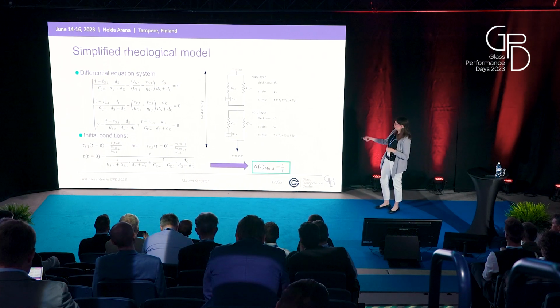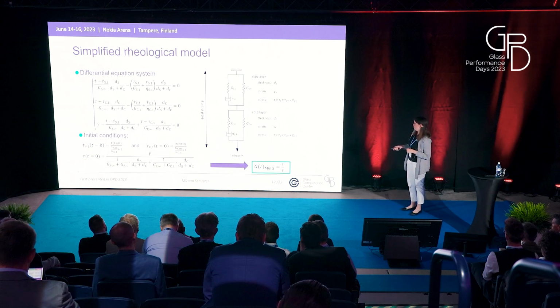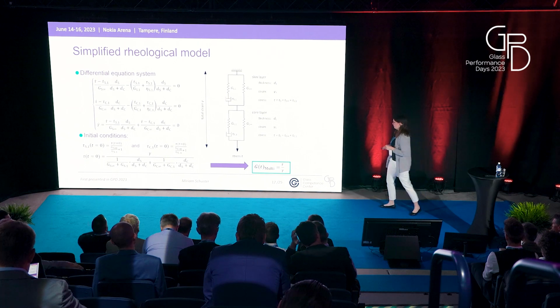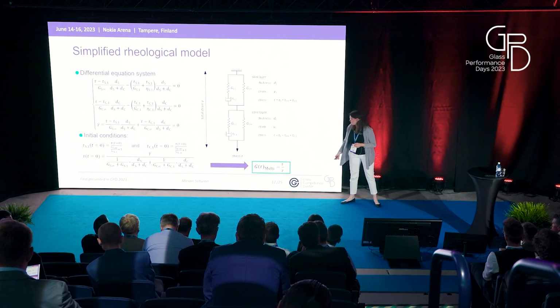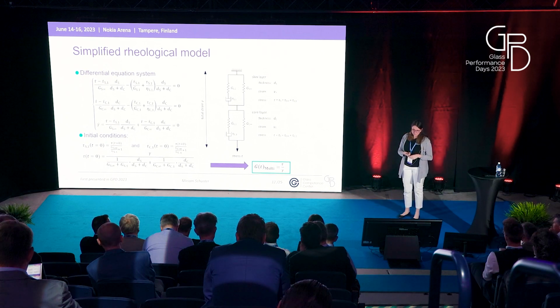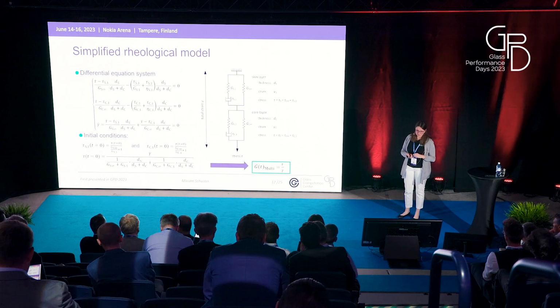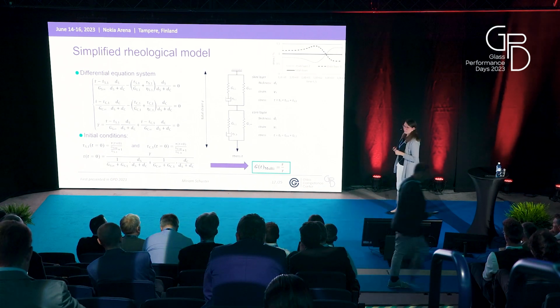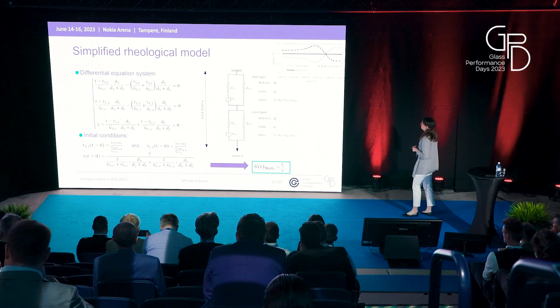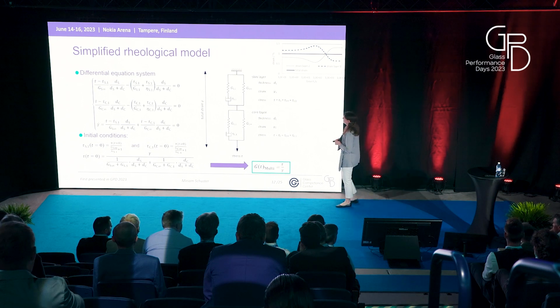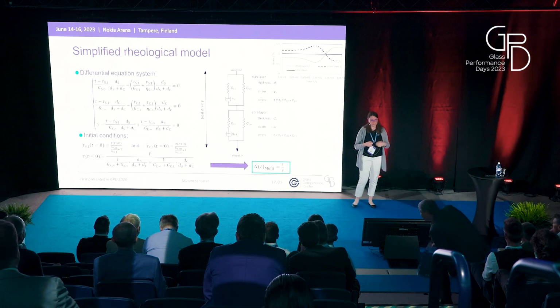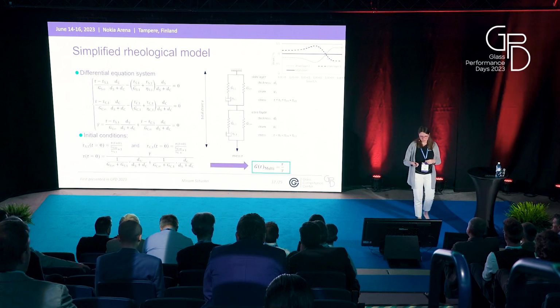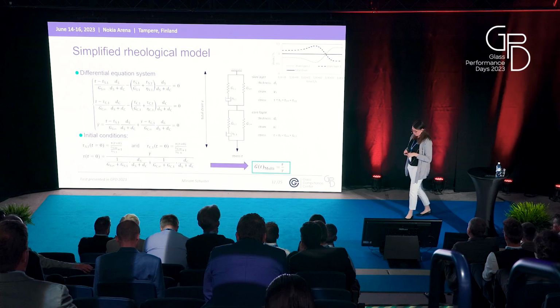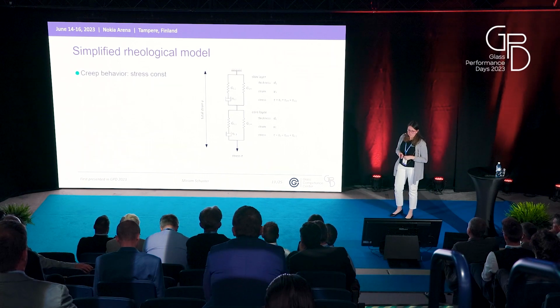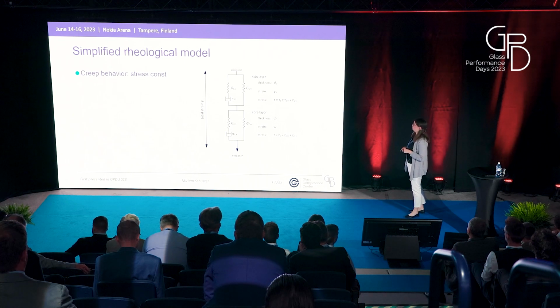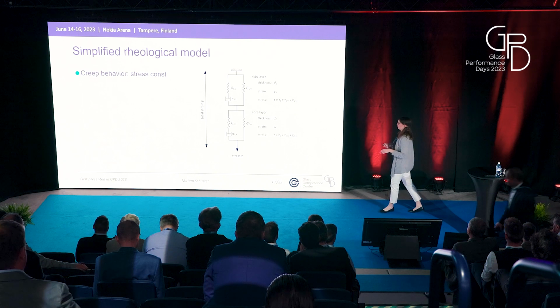the stress response for this multi-layer, and with the stress response and the applied strain, we can calculate the effective modulus for our multi-layer. At this point, I want to point out that even if the total strain is constant, the strain in the individual layers may change over time. And this means that the different layers influence each other, and this makes the solution of this differential equation system very long.